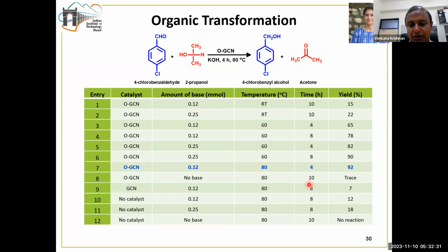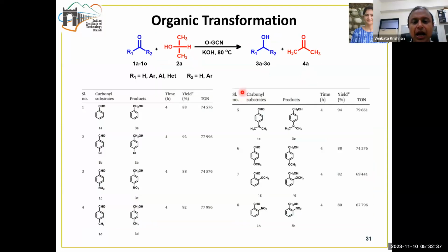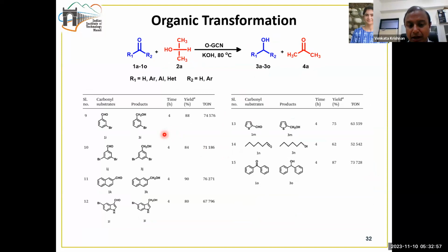And we have done a detailed optimization of the reaction conditions. In one of the conditions, we achieved a very high yield of 92%. We also examined the wide scope of this material by doing a detailed substrate scope study, wherein we have taken different forms of carbonyl substrates and used our catalyst to form the corresponding products, and we got them in high yield and high turnover numbers, which are shown here. The substrates we have tried are not only aromatic but also aliphatic, and our reactions go on with both the aromatic and the aliphatic substrates, with both electron-withdrawing and the other types of functional groups involved in this material.